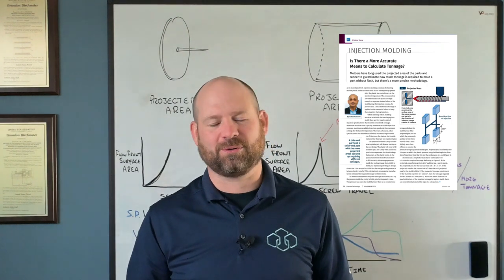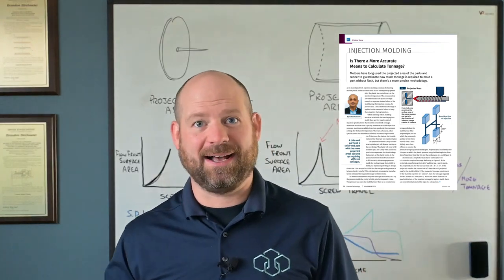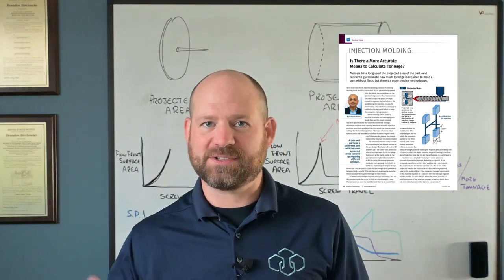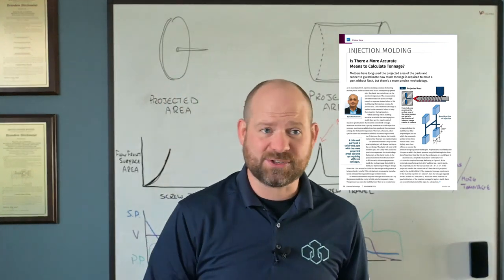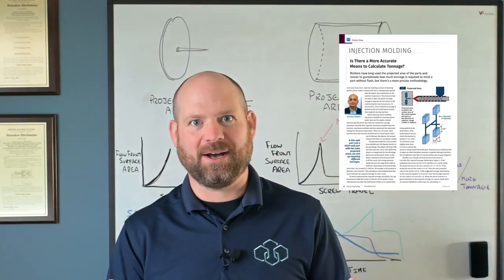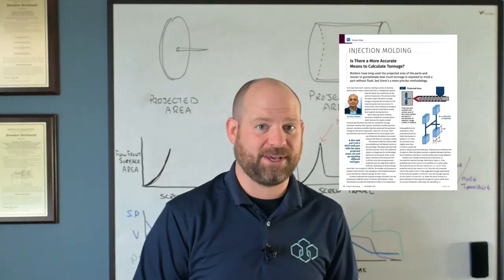Suhas provides a really cool tool for figuring out tonnage using a high tonnage setting. And then again, once you establish your process, reducing tonnage to start seeing changes in, say, part dimensions or part weight. Again, a methodical, systematic, specific approach to determine optimum tonnage for your application.